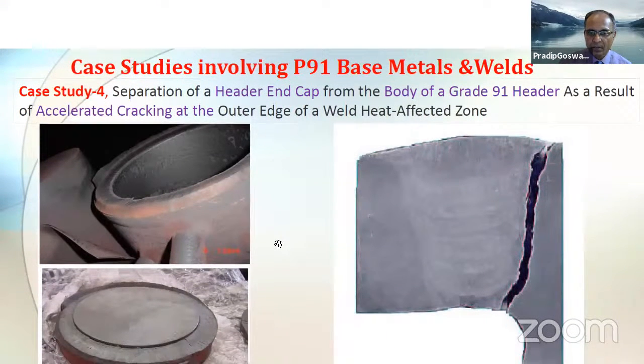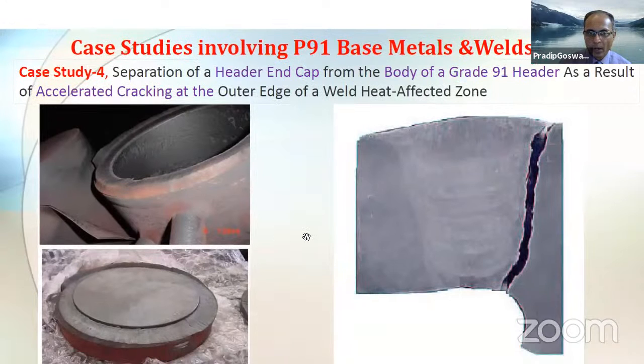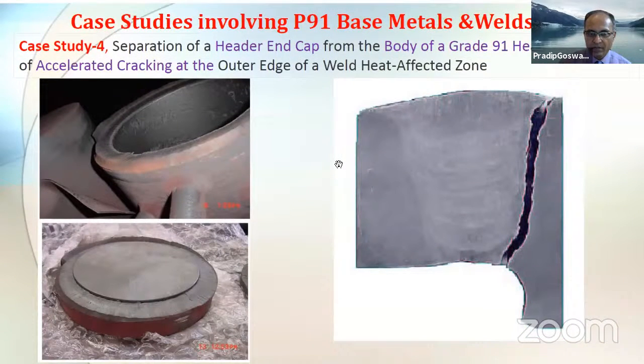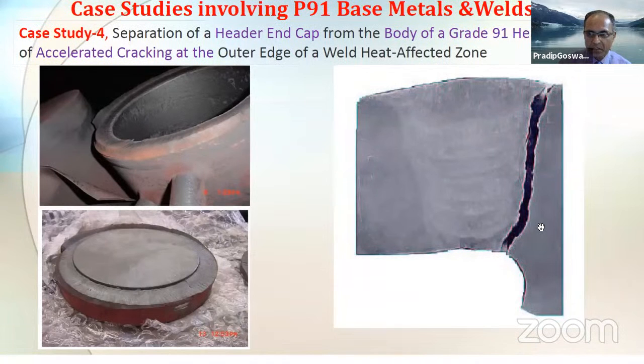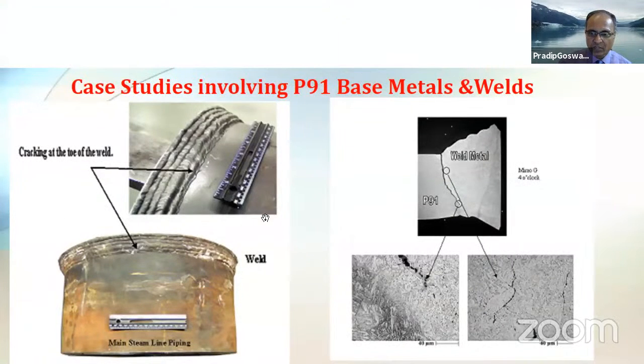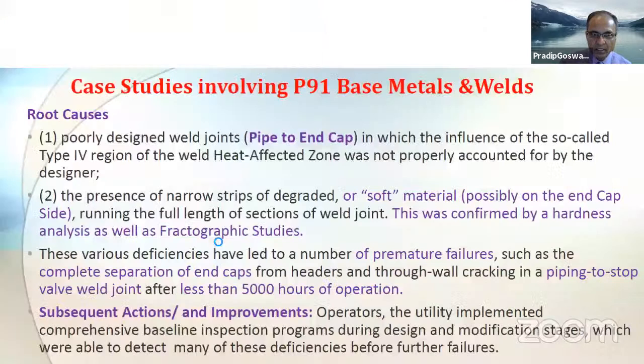This case study is on the typical failure of a component, a header cap, in service. As you can see from the photographs, this is the component shown here. The failure was a wide mouth failure, which propagated right through the entire thickness of the weld. These are pictures taken on the exterior of the weld, which show typical cracking at the toe of the welds.